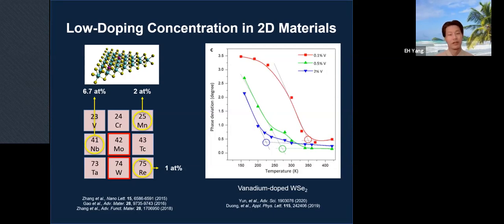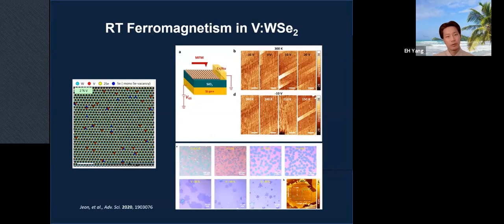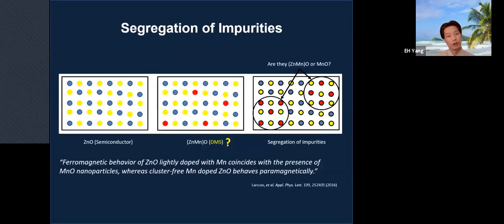This is the interesting part. This paper was published recently, in almost the same time frame as our publication here. It was published in Advanced Science, and this is a very nice paper. It also shows room temperature ferromagnetism in vanadium-doped tungsten diselenide. But the magnetic field was measured only at local scale using magnetic force microscopy. This is very nice work. However, you need to think about this segregation issue.